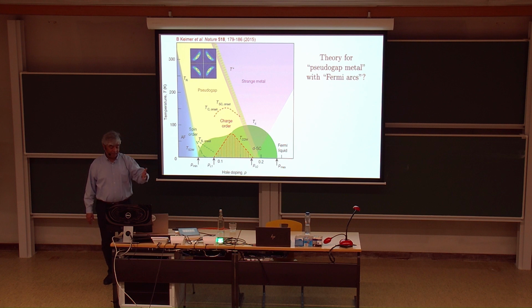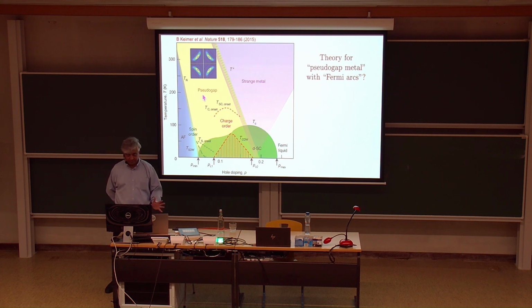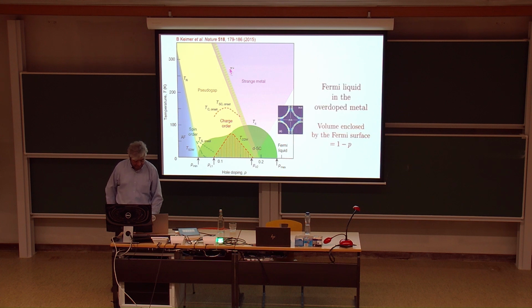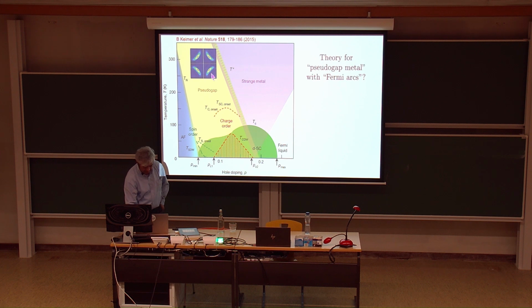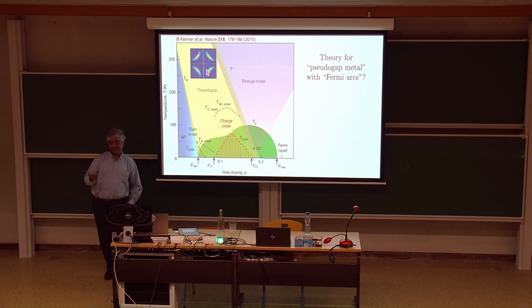Okay, so what about, let's go to the metal that you see at lower doping, where the Tc is high. So there we have a metal, which people call a pseudogap. And one of the reasons it's called a pseudogap is if you look at the Fermi surface in photoemission, this is actual photoemission data. I'm sorry, I should have put the reference. Then you see these gaps. There's nothing here. If you compare it to the Fermi liquid, you get a complete arc. But what happens here is that there are no intense low energy excitations in this region of the momentum space once you're in the pseudogap. Okay. So you just get these arcs, and nobody's theory has arcs. So anyway, they're called Fermi arcs just as an experimental summary of what's actually seen.